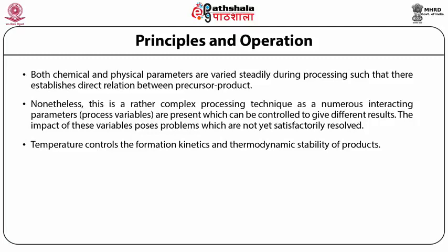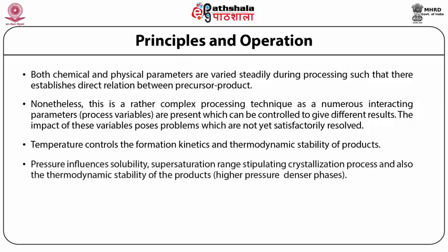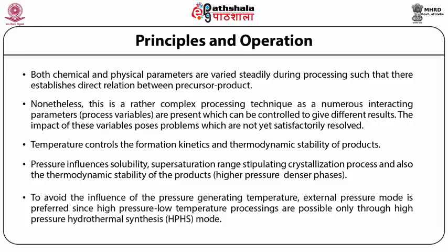Temperature controls the formation kinetics and thermodynamic stability of products. Pressure influences solubility and supersaturation range, stipulating the crystallization process, and also the thermodynamic stability of the products. That is, high pressure gives rise to denser phases. To avoid the influence of the pressure-generating temperature, the external pressure mode is preferred, since high pressure, low temperature processings are possible only through the high pressure hydrothermal synthesis mode.